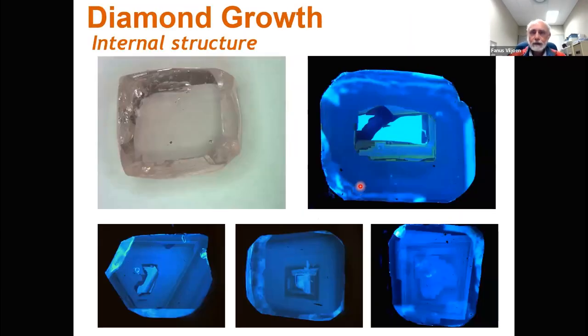Right, how do diamonds crystallize? We think they crystallize as a series of pulses, and we know that because you can cut a diamond into plates. It's a very simple process. And then if you look at the interior of the stones using cathodoluminescence, if you irradiate diamonds with electrons using an electron gun, you get what is known as cathodoluminescence. The diamonds essentially glow under the electron beam. And so you can see the internal stratigraphy of the diamond. For example, this diamond has a core which may even have suffered a tectonic event, in which case it may have deformed. It then healed in a subsequent regrowth event, as you can see here.